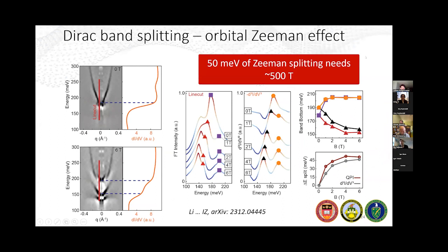We thought about this long and hard. The short answer is we're not completely sure why it would completely saturate, but I can give you an answer for why it would taper off, why it would become slower. If you have a Dirac dispersion and you gap it with a very small gap, the Berry curvature, which is proportional to these orbital moments, is going to be very large. You can think of it as inversely proportional to the gap. If you apply magnetic field, you basically round off the bottom of the Dirac cone, so the Berry curvature becomes slightly smaller at the bottom, therefore the orbital moments are smaller, therefore they couple less with the field. Our theories couldn't directly compute this in a full-scale model, but this is the gist.